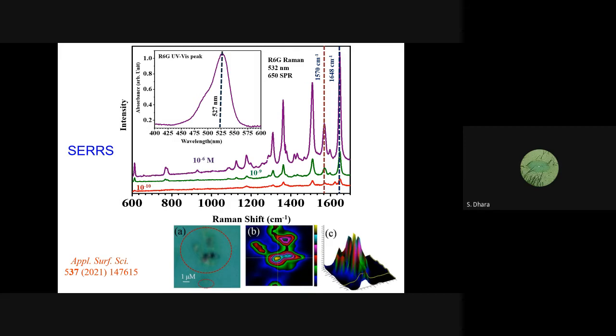And here we can go even to 10 to the power minus 10 molar. If you see the red one, 10 to the power minus 10 molar, we could go. We also looked at one of the Raman modes, the 1648 Raman mode. We used Raman imaging. That means we scan the whole area with a particular sector and measure the intensity. See this second image, image B, showing the color distribution, and according to the color bar, yellow is the strongest.